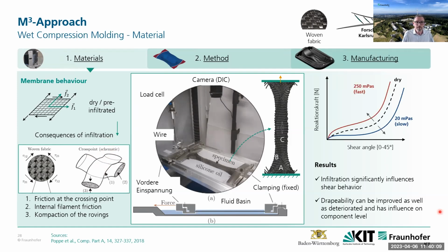The new test rig is shown here. So you see here the fluid basin. So that's a test rig that has been developed. We call it the IBET, the Infiltrated Bias Extension Test, where the shear deformation was measured in a fluid basin at complete wetting. In that case, the camera from the top is measuring the current shear angle in the center of the specimen. Obviously, we have the 3 zones: no shear, half shear, full shear in the center of this